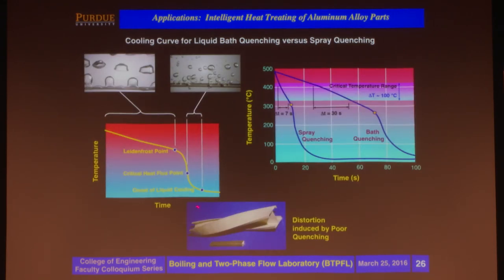Now, I'm borrowing the same pictures from before to show you what we have here: temperature versus time, what happens as the quench proceeds. And what happens typically in most operations, I've actually designed a lot of aluminum plants, heat treating plants, is that they bring a lot of parts, different shapes and sizes, and throw them in a basket and put them in a bath.